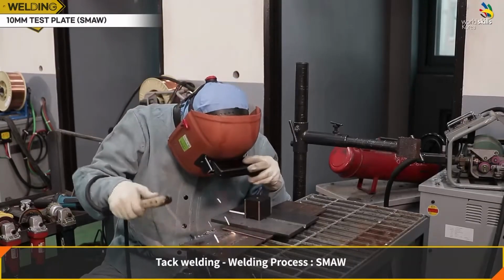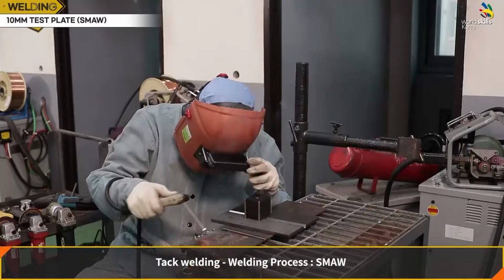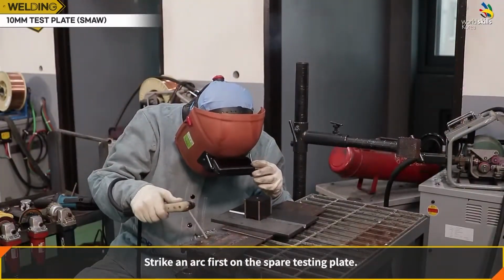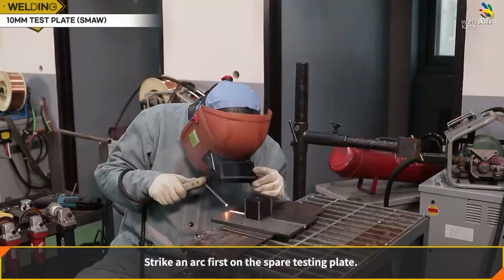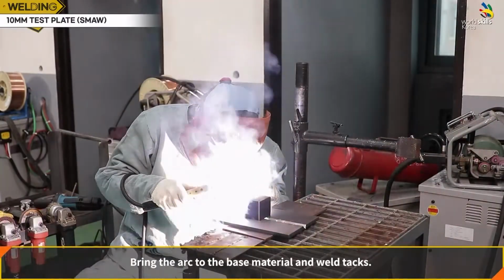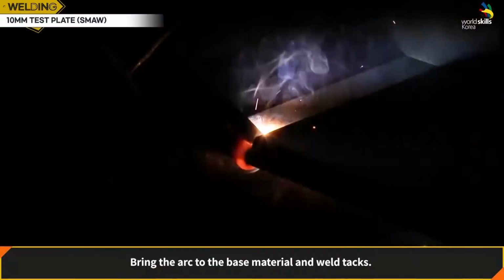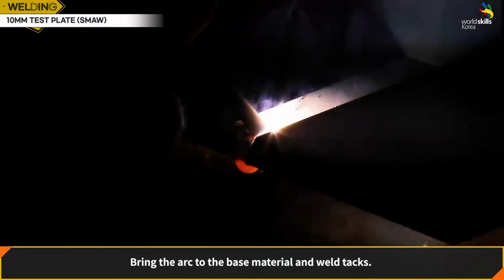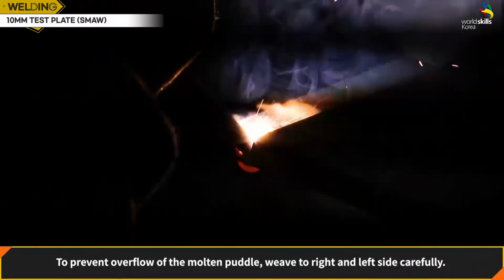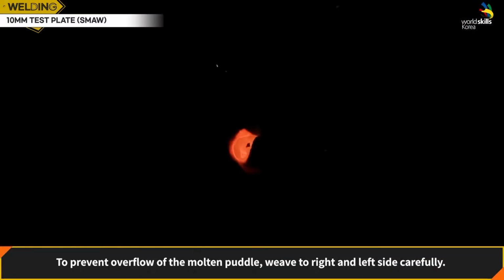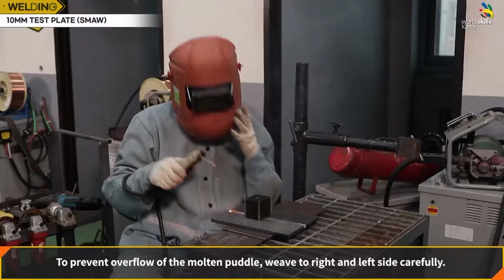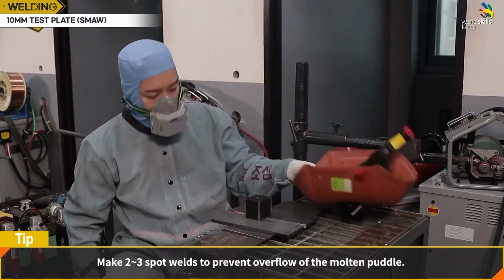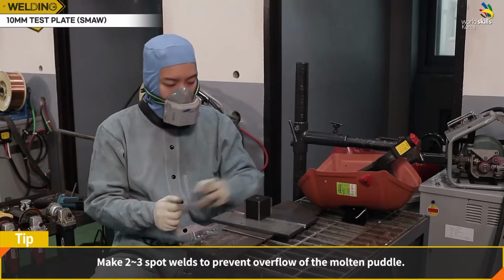Tack welding. Welding process SMAW. Strike an arc first on the spare testing plate. Bring the arc to the base material and weld tacks. To prevent overflow of the molten puddle, weave to the right and left side carefully. Make 2 to 3 spot welds to prevent overflow of the molten puddle.